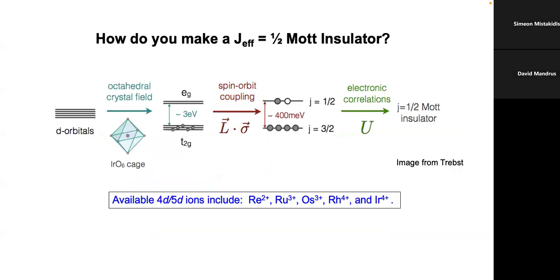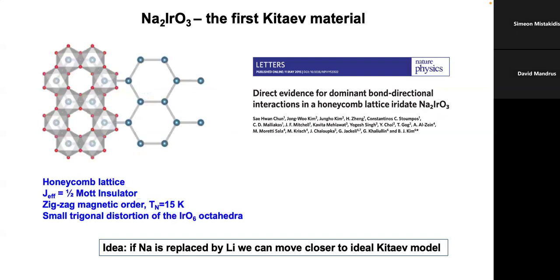And so this J effective 1/2 is essentially in the strong crystal field limit. You have a very strong crystal field and various splittings due to crystal field, spin orbit coupling, and so forth. And this J effective J equals 1/2 state can be realized by these ions right here: iridium, ruthenium, osmium, rhodium. And at that point, there was a global search to try to find these materials. The first one discovered was sodium 2 iridium O3.